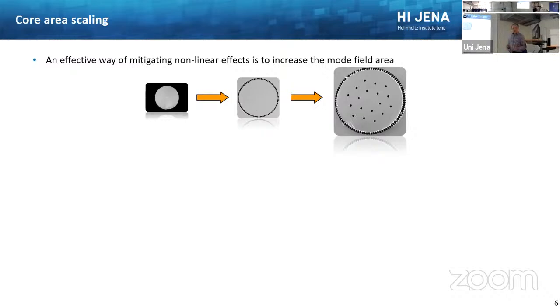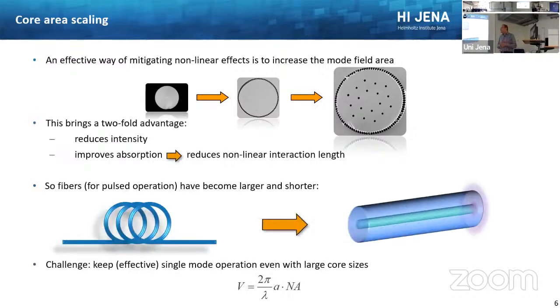This larger diameter has two advantages. It, of course, reduces the intensity again, so you can go to higher pulse energies. And it also increases the absorption because you have more area, more active material. So the length you need for your amplifier can also be reduced, which also reduces the effect of nonlinear effects. When you go to higher pulse energies, you regularly go from standard flexible fibers that are quite long, that you see on the left side in the sketch, to what we call rod-type fibers. These are not bendable anymore and have a thickness of about 1 or 2 millimeters and a length of about 1 meter.